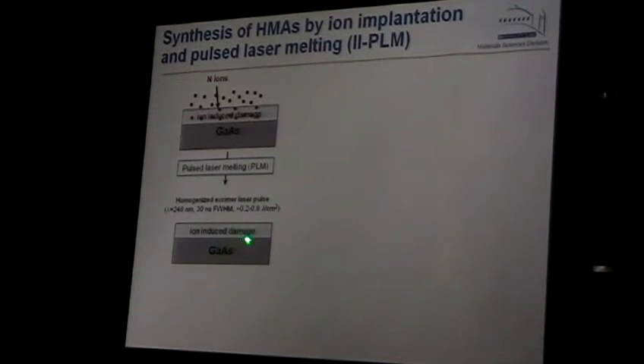You accelerate nitrogen ions, so you produce the damaged layer, but with nitrogen. Nitrogen is sitting there because it cannot escape. Everything is at room temperature. And then what we do is we use one pulse of the excimer laser and melt the top layer. When you melt the top layer, you get this.